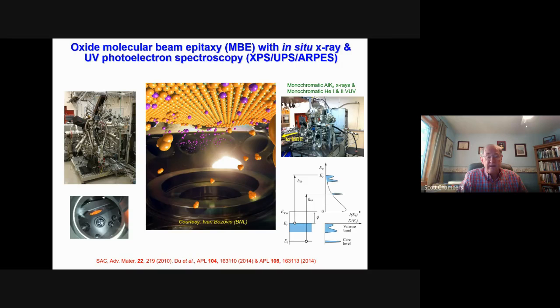And we find that of all the tools that you could have hooked up to an MBE system, we think that XPS and UPS, that combination, is probably the most versatile and useful tool that you can have on an MBE system, and that's why we do it. So we can get data on crystalline films that are freshly grown, they haven't gotten dirty yet, and therefore we can really capture them in their pristine state.